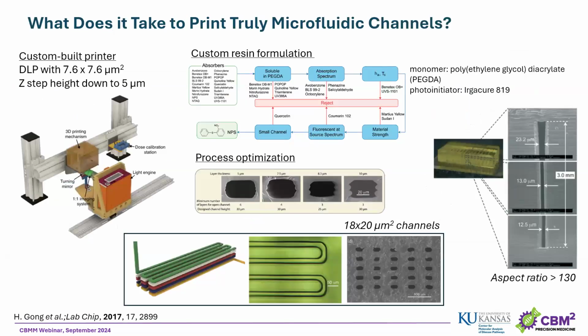And I mentioned earlier that it's so simple to use a 3D printer. However, if you really want to push the limits of the research, you have to spend a lot of time improving, both on the instrumentation side and on the chemistry side, using different photoinitiators and different custom resin formulations. And this is an example from Professor Woolley's lab, when they built their own printer with a voxel size down to 7x7, roughly 8x8x5 micrometers, and by optimizing different resin formulations, they were able to actually push the limits and make channels down to a 20x20 micrometer cross section.